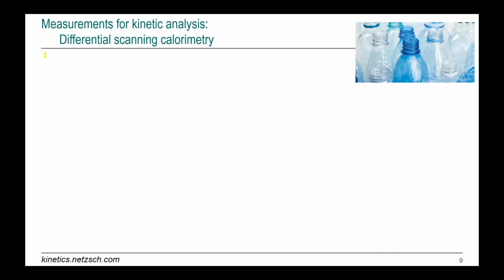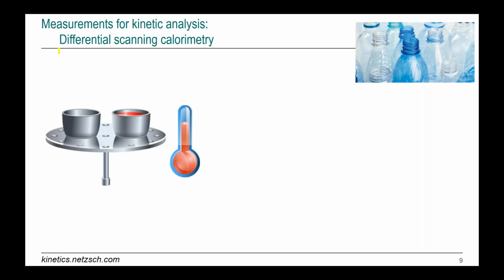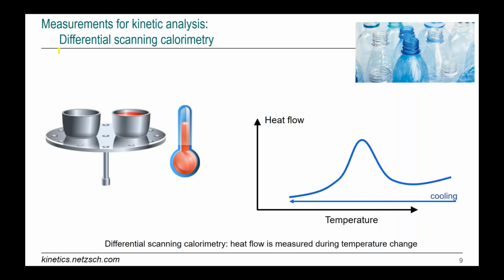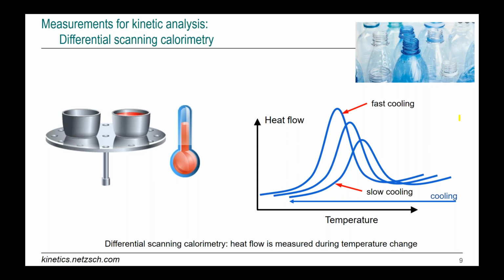Here are thermoplastics. For thermoplastics, during crystallization, we know that heat energy is produced. We can again use differential scanning calorimetry, but in this case we cool from high temperature to low temperature, from liquid state to solid state. Again we measure heat flow and the heat produced during crystallization. We can cool fast or slow, giving different curves, and these curves are used for our kinetic analysis.